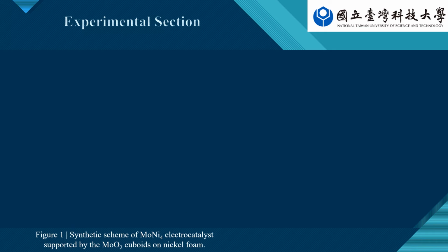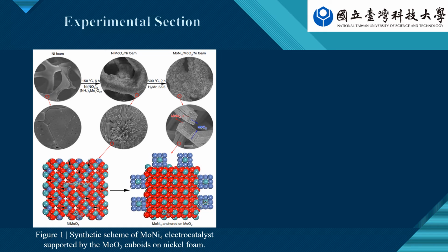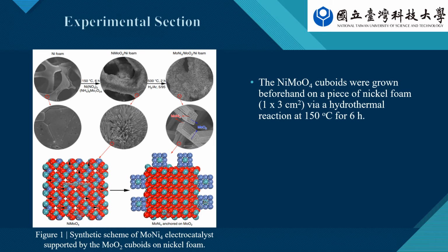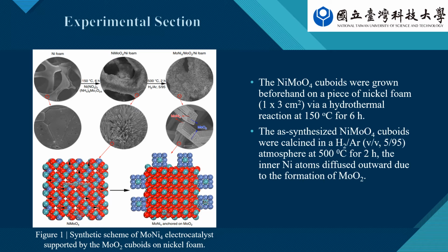In the experimental section, MoNi4 nanoparticles with a size of 20 to 100 nanometers are constructed in situ on the MoO2 cuboids by controlling the outward diffusion of nickel atoms when the previously synthesized nickel molybdenum oxide cuboids are heated under an argon and hydrogen atmosphere at 500 degrees Celsius for 2 hours.